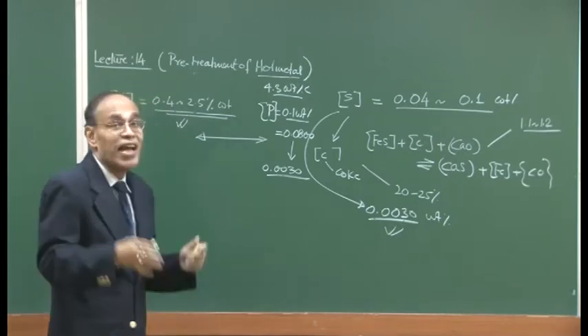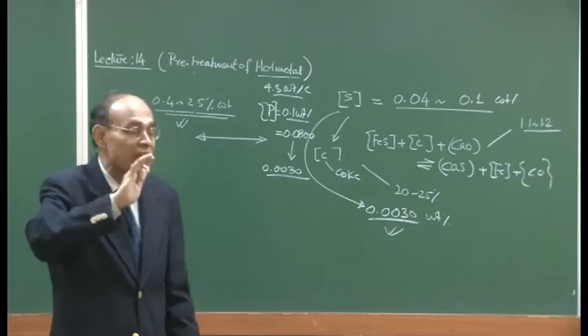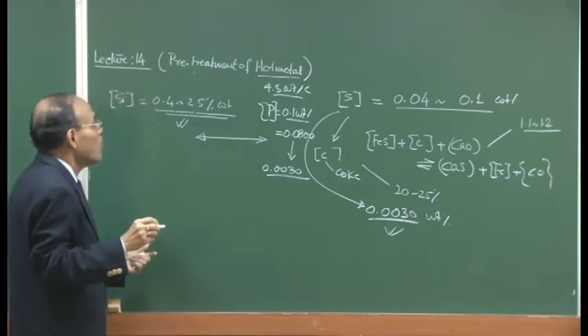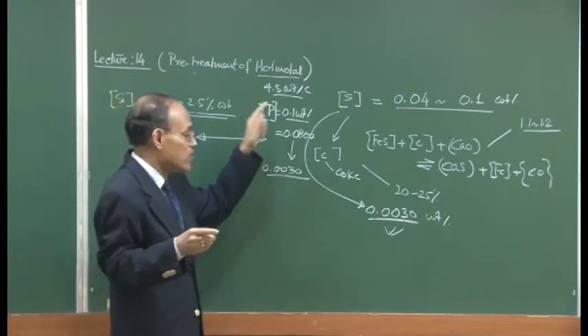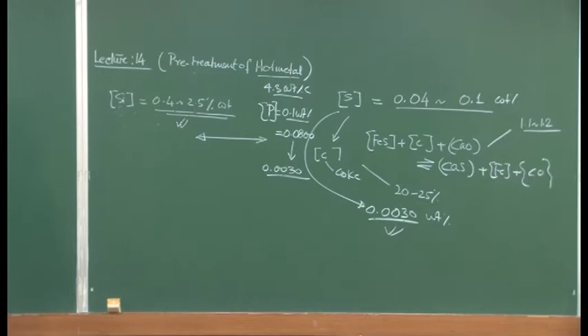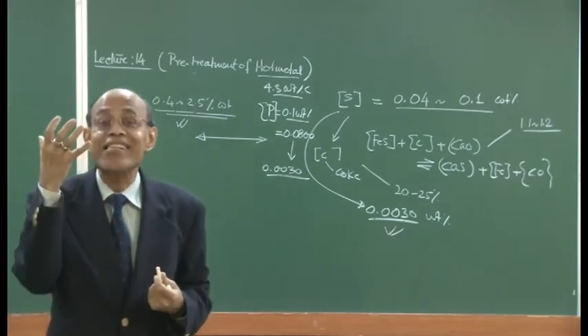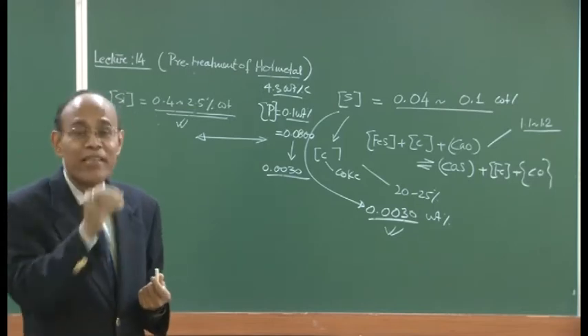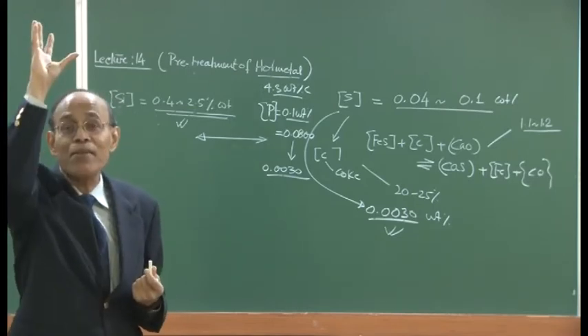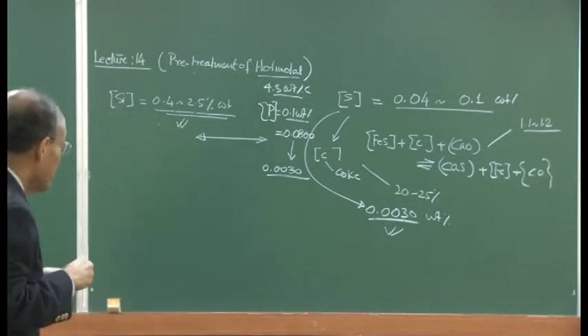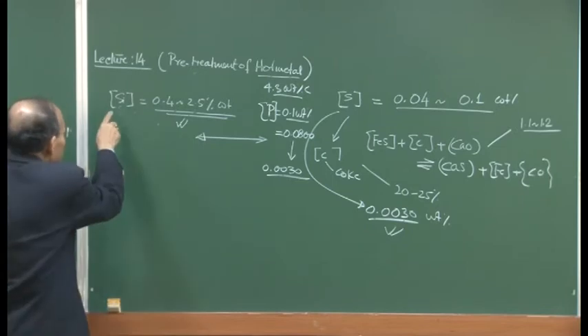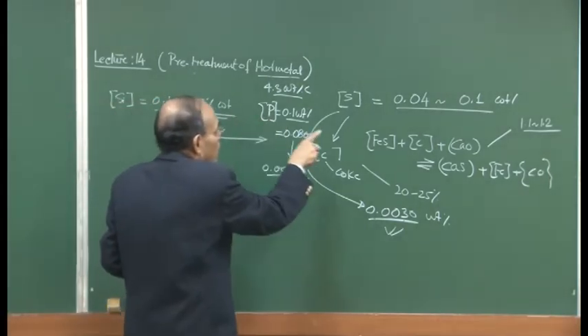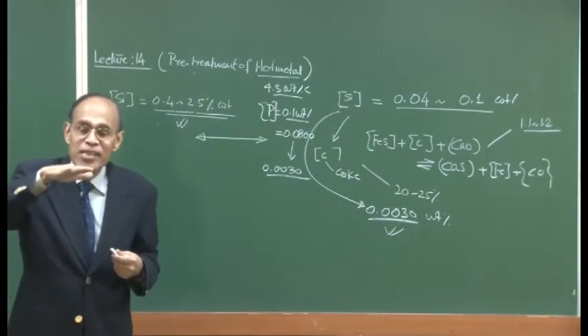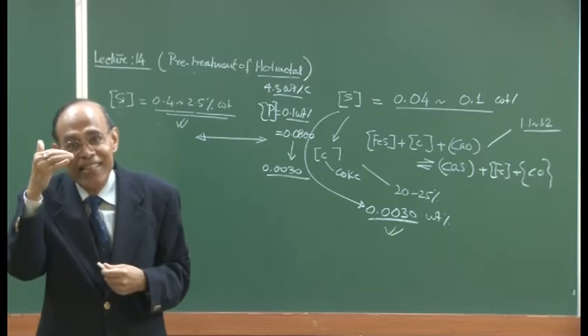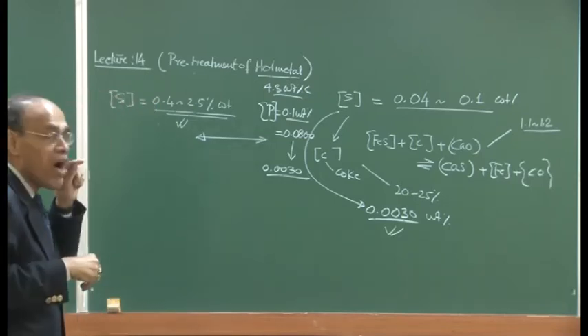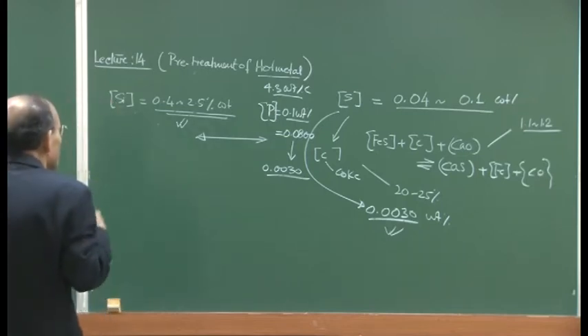But if you say, sir, I have controlled through pretreatment my sulfur content, my phosphorus content, and there is nothing to be eliminated as far as these three elements are concerned, that is silicon, sulfur and phosphorus, you have landed in a situation which is called slagless steel making. That means carbon will oxidize, carbon will make the steel making autogenous, but because it is going to escape as CO, no slag is going to be generated. So, therefore, controlling the silicon content, phosphorus and sulfur through pretreatment is a move in the direction of less and less slag during the steel making process, a march towards slagless steel making, or minimal slag in the steel.